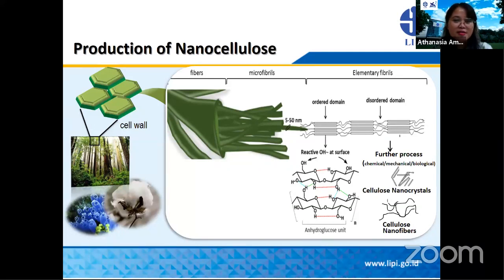Okay, talking about the structure of the nanocellulose, for example, the structure of the nanocellulose in the plant cell, it consists of fibers that we can easily see by our eye. But then when it goes into the microfibrils, every single fiber consists of multiple microfibrils, and these microfibrils have about 5 to 50 nanometer diameters. And each of the microfibrils also contains both ordered domain, which is the crystalline domain, and also amorphous domain.